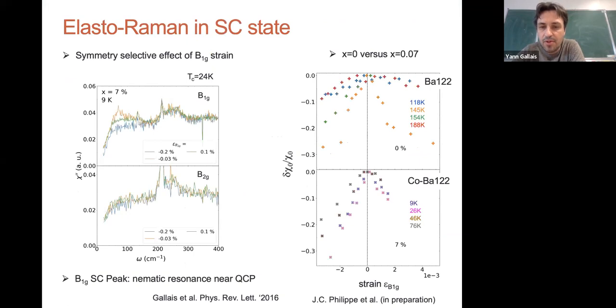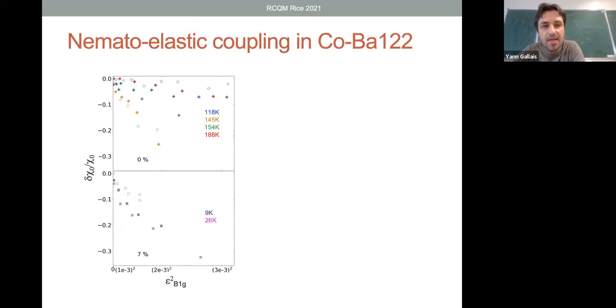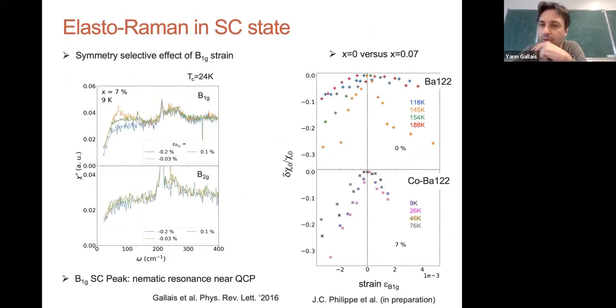Now, the key point I wanted to mention is that you can actually do the same kind of measurement in a superconducting composition. So in a sample where TC is 24K, very close to optimal doping. This is the data on the right, where I plot delta chi node over chi node for both dopings. And what is immediate, this is the same scale in terms of the B1g strain, is that the data, even in the superconducting state at 9K, in purple, seem to be very similar to the one at 0% close to TS.